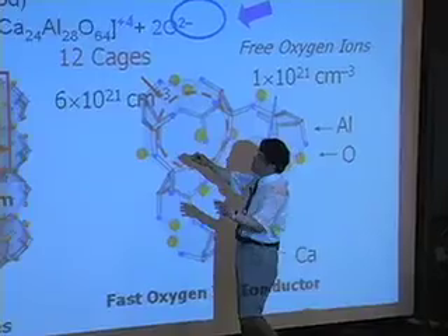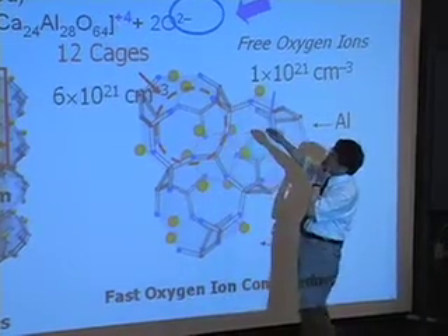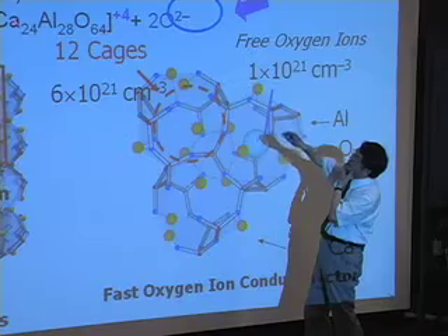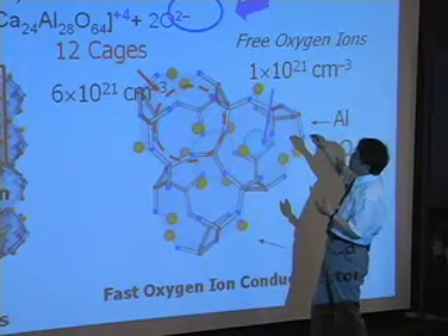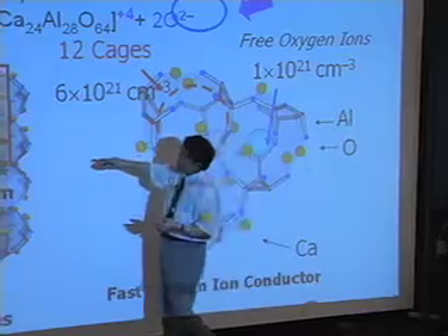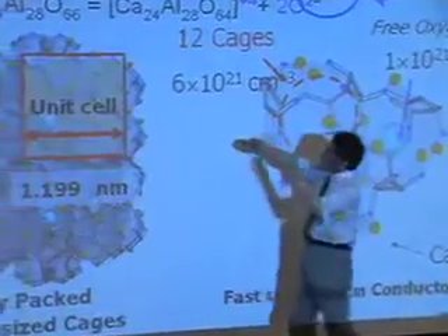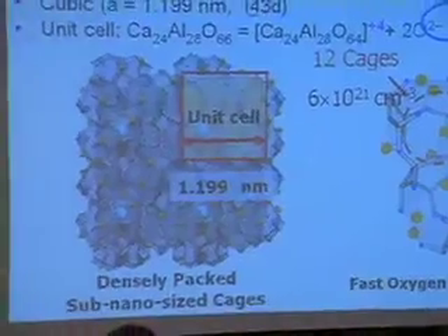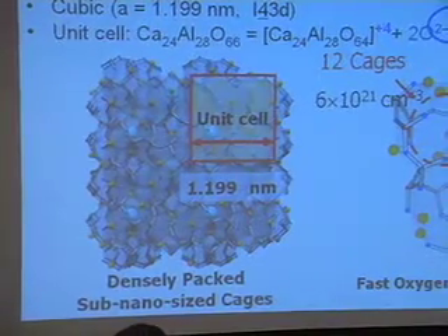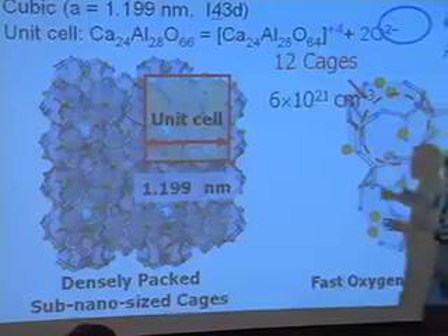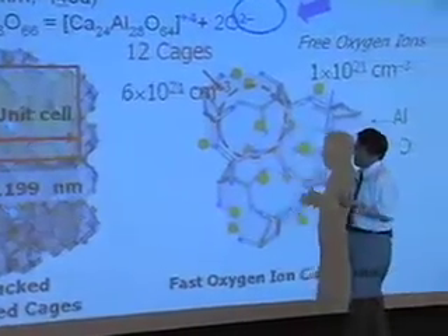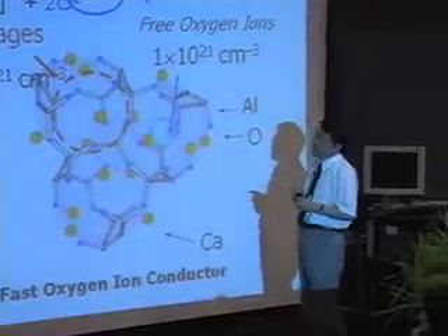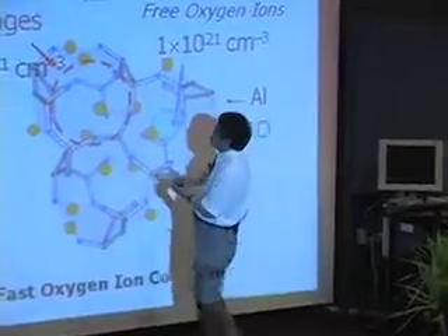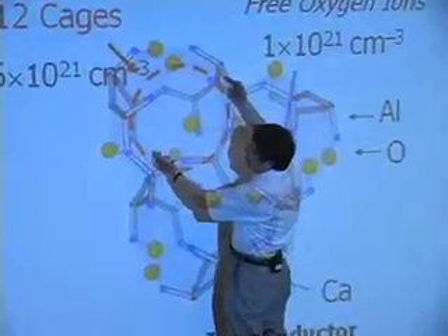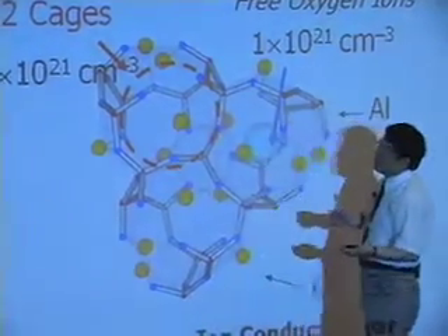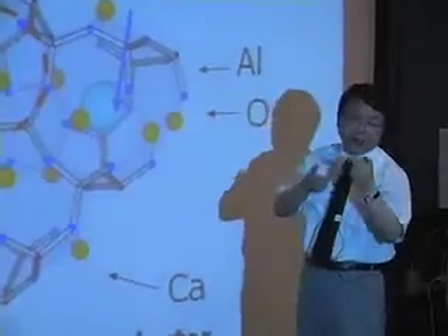The cage wall has a positive charge of +4. To compensate this positive charge, 2 oxygen ions are distributed in 2 out of the 12 cages like this, so the occupation of O2- in a cage is only 1/6—5/6 is empty. Quite interestingly, the diameter of the cage is almost double the diameter of the O2- ion.